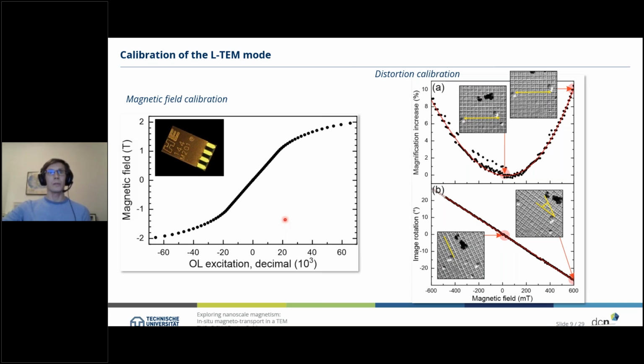But if we change the main lens of the electron microscope, of course we will have a strong impact on the beam itself, on the image, on the magnification, and so on. That we also need to take care of, and that is shown here on the right-hand side, where we start by looking at the image rotation as a function of the magnetic field. You see that when we apply a magnetic field, as we expect, we have an image rotation which is linear with the applied magnetic field. So that is quite easy to compensate afterwards in the post-processing of our experiment.